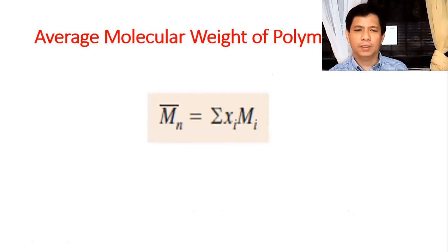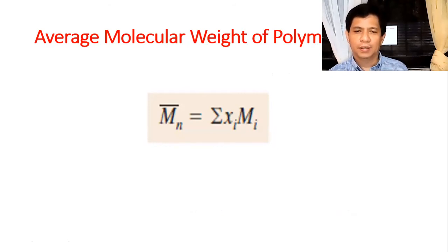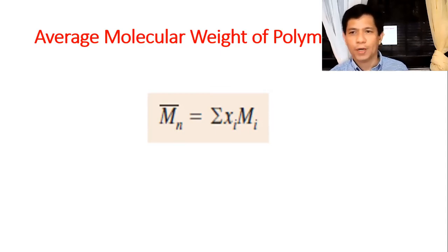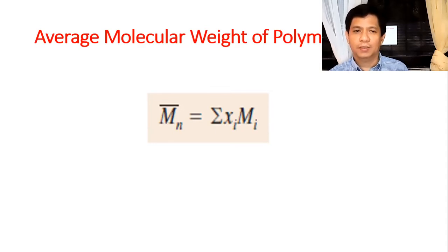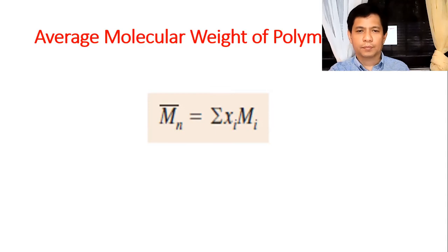How do we calculate the average molar weight of a polymer? You multiply each fraction by its molar mass Mᵢ and take the sum: M̄ = Σ(xᵢ × Mᵢ). For example, if you have two fractions — one at 1,000 and one at 2,000 g/mol, each at 50% — you get 0.5×1,000 + 0.5×2,000 = 1,500 g/mol. The key takeaway: molecular weight of polymers is in the thousands of grams per mole.